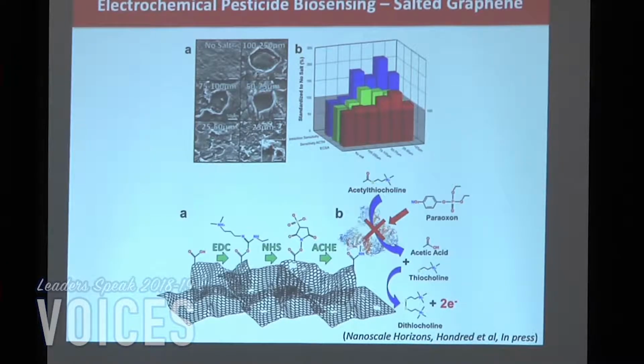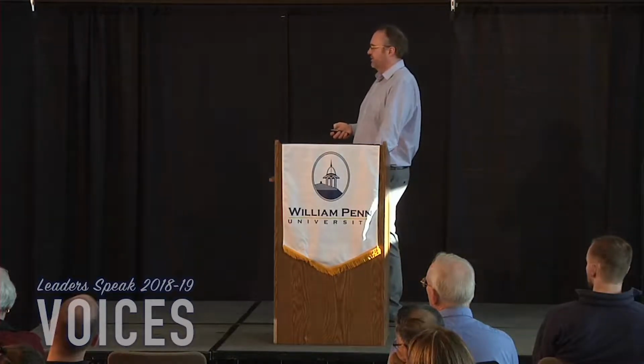So that opened up a lot more surface area. Now we have these larger micron craters that are larger than those smaller nanoscale flakes. So we just added a lot more surface area. We were able to bind an enzyme to that surface and do the testing, and we were able to get the detection limit under a nanomolar just by tuning that surface. So that just shows you, just by making these small tweaks to the fabrication process, you can really change the electrocatalytic ability of these nanomaterials.